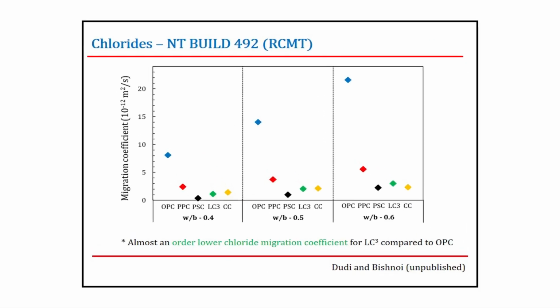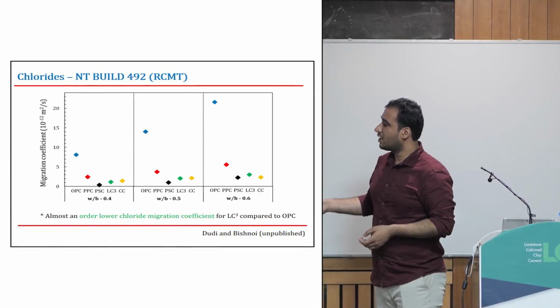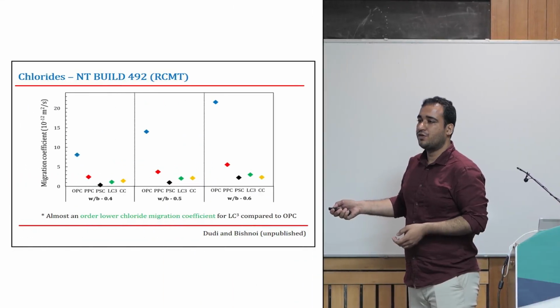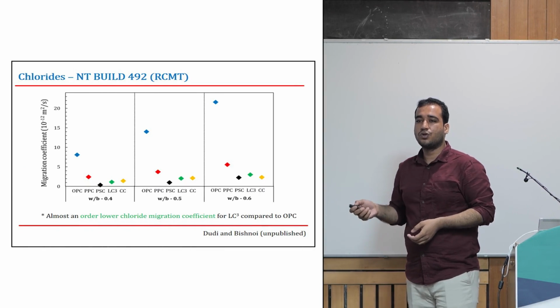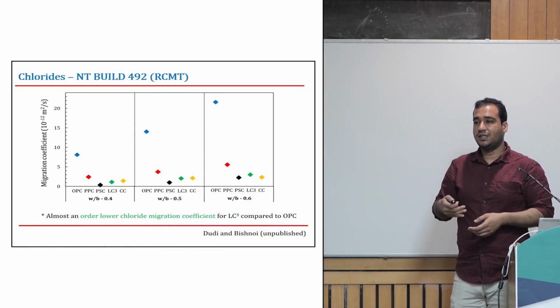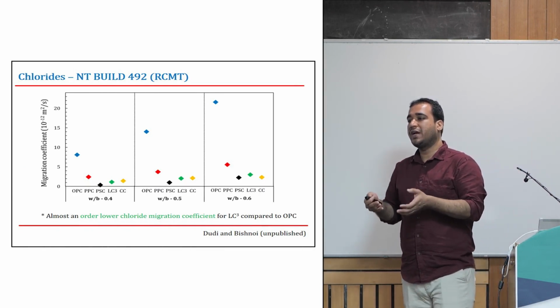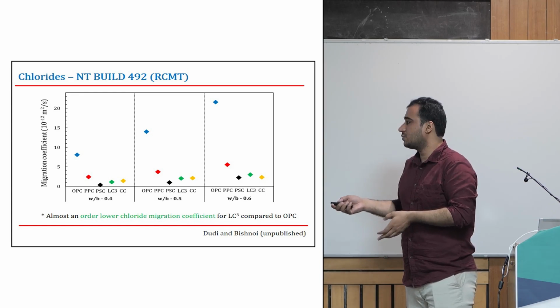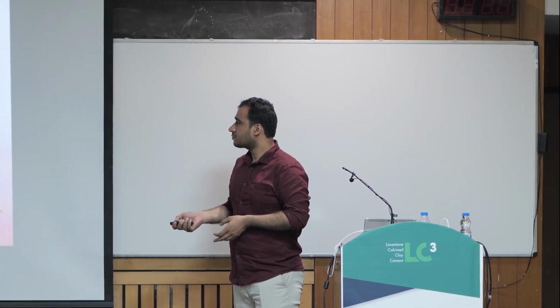These are some more results that I was talking about, the apparent diffusion or migration coefficient. You see, compared to OPC, the blue dots, the green dots are much lower. Even at a water to binder ratio of 0.6, you have a lower migration coefficient compared to OPC at 0.4. That's how good your pore refinement is, and that's how enhanced the chloride binding is in the blended system with calcined clays.